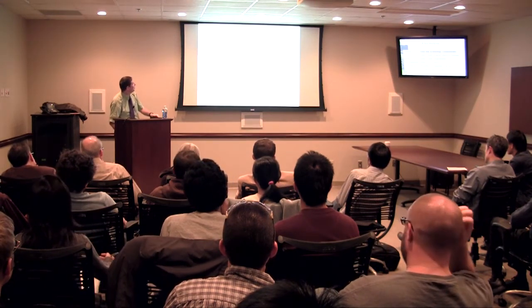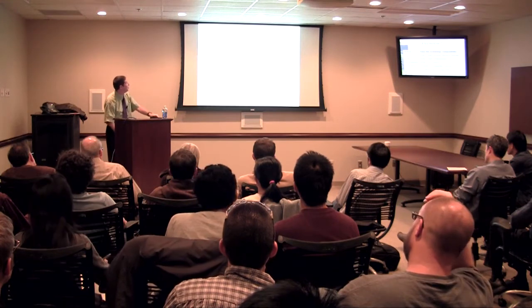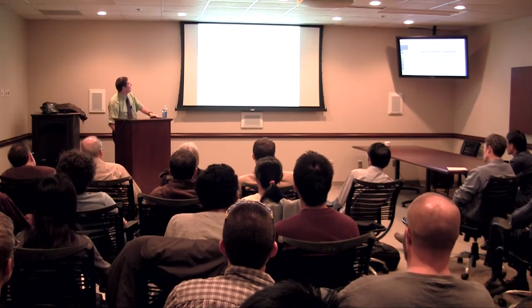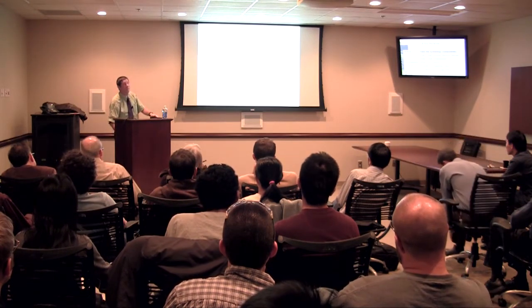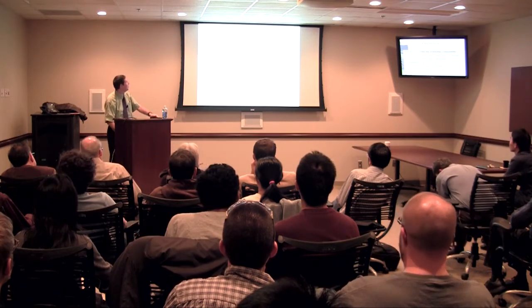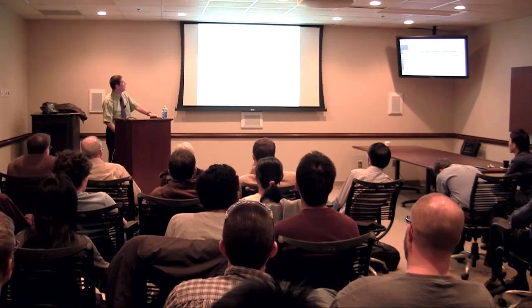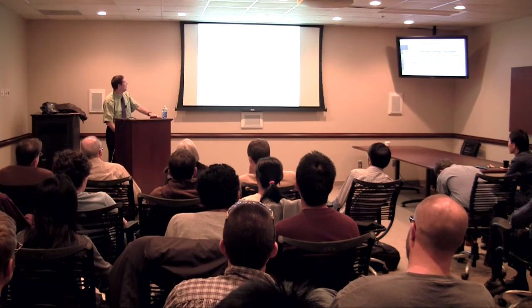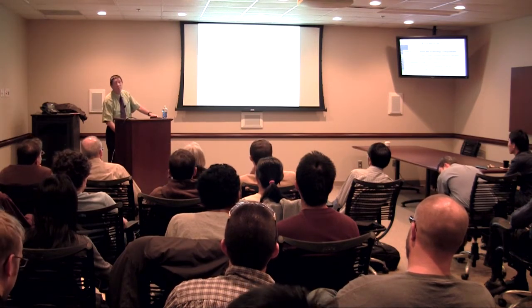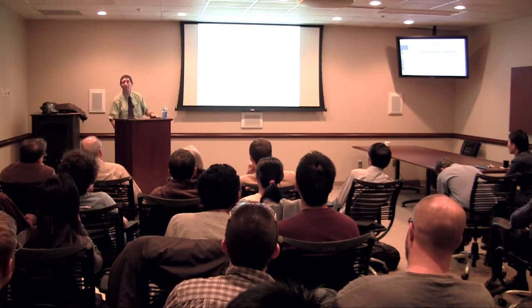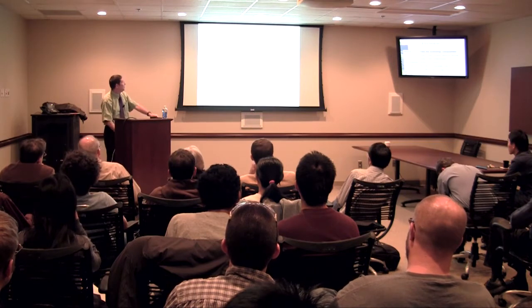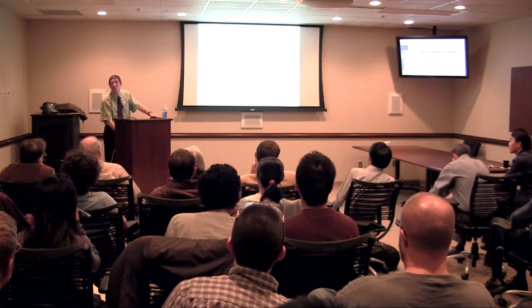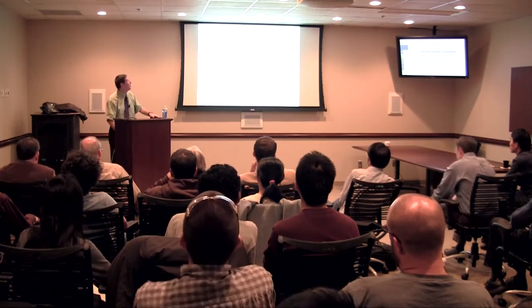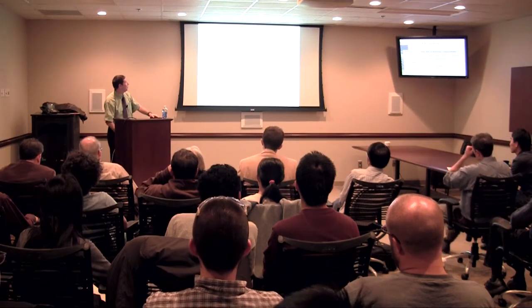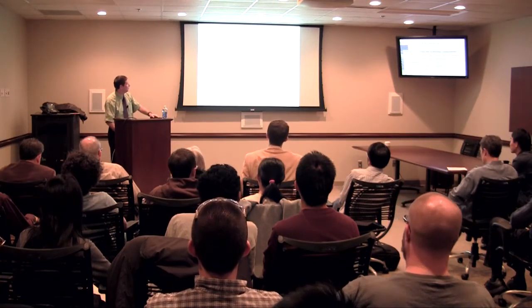Electroless, if you look at metal deposition, and this is for the students here, you can do PVD, it's not biocompatible. It's very difficult because it's in a vacuum system. CVD is not compatible because of high temperature. Electroplating is very difficult because the substrate is insulated. Now, electroless and ALD are two good solutions to deposit on polymers or on insulators.